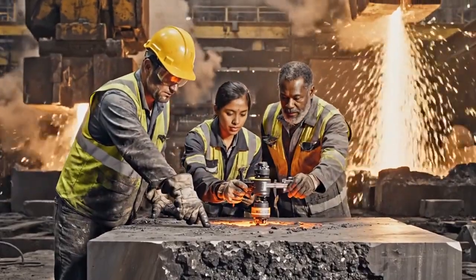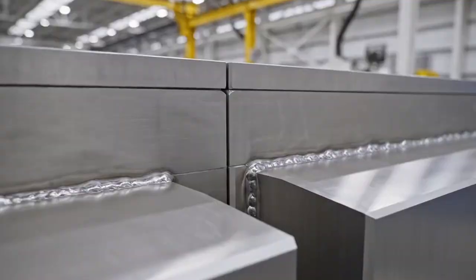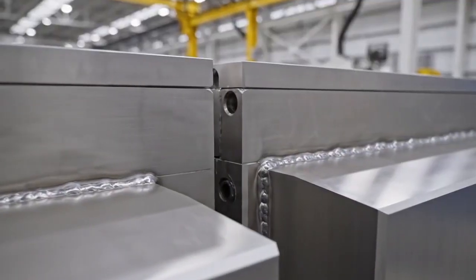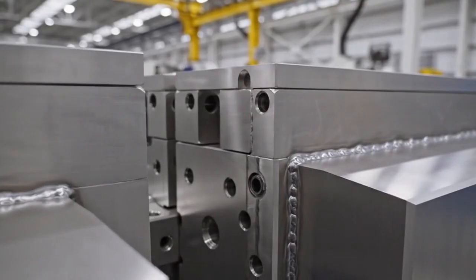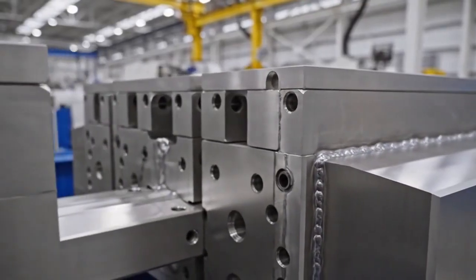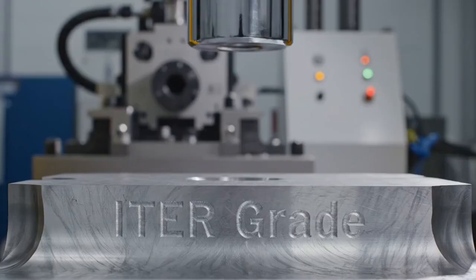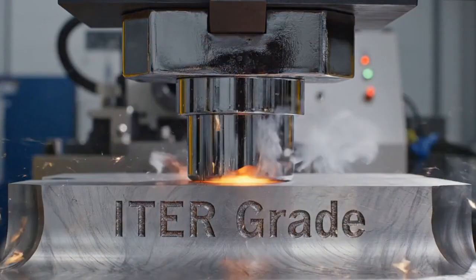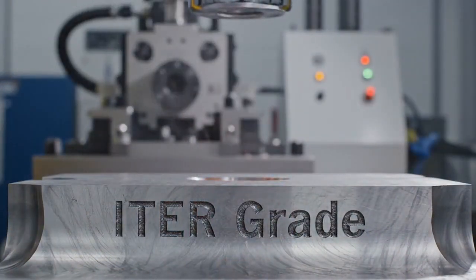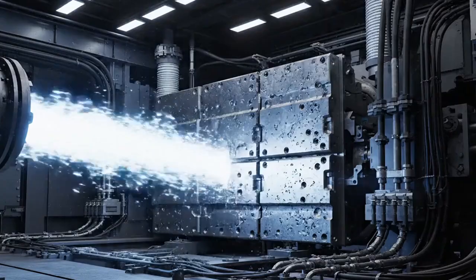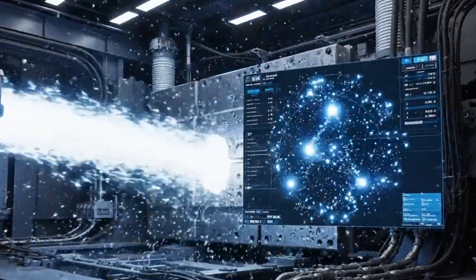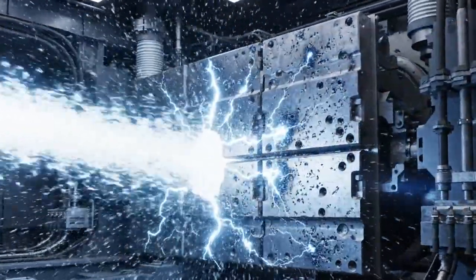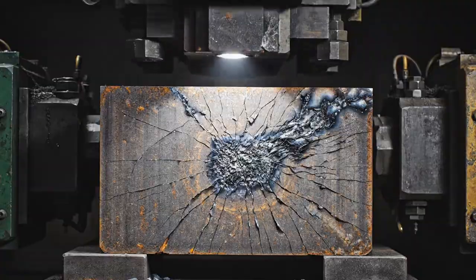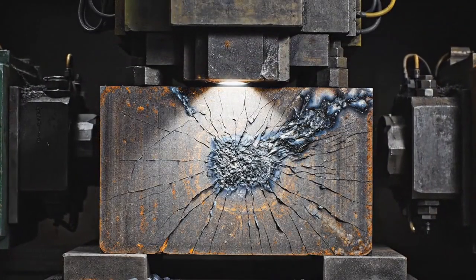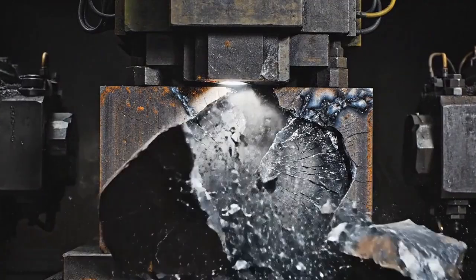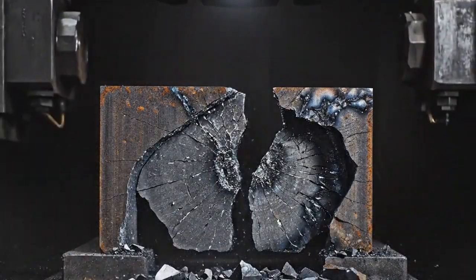This is not constructed from standard industrial metal. The entire double-walled structure is forged from a highly specialized, nuclear-grade alloy known as 316 LN-IG stainless steel. The IG stands for ITER grade. This specific material was engineered to withstand immense mechanical stress while simultaneously resisting the intense, high-energy neutron flux generated by the fusion reaction. Standard steel would suffer from severe atomic embrittlement and rapid structural degradation under such extreme nuclear bombardment.